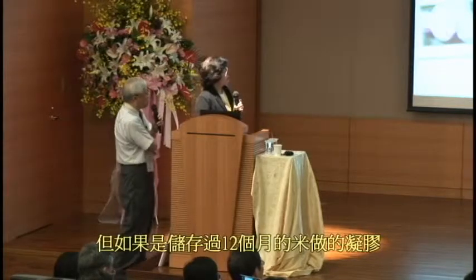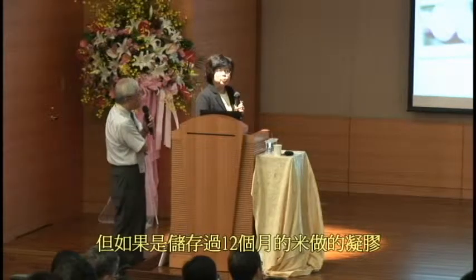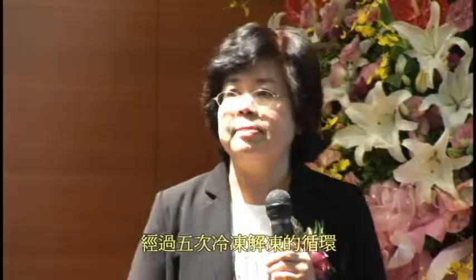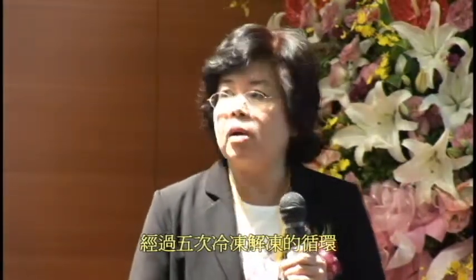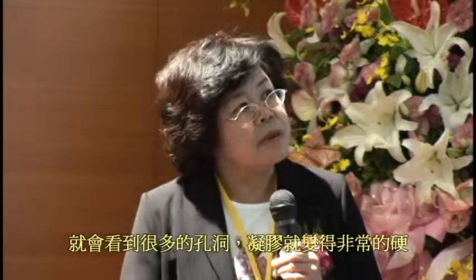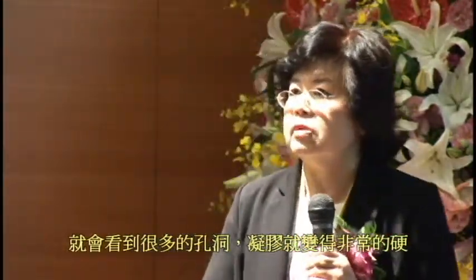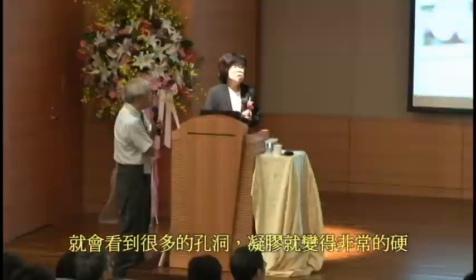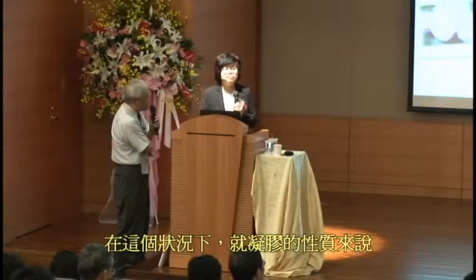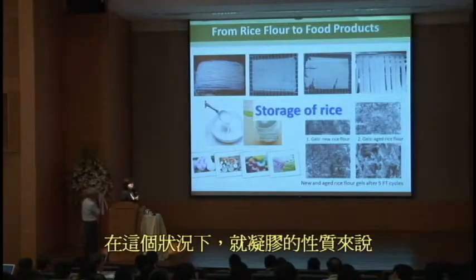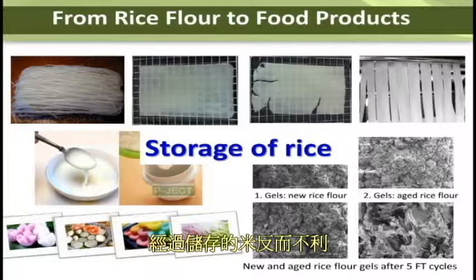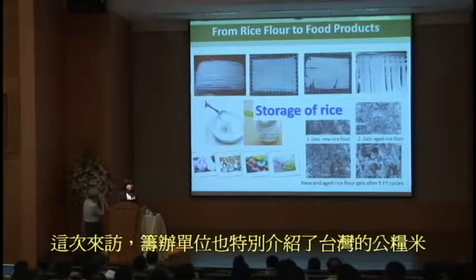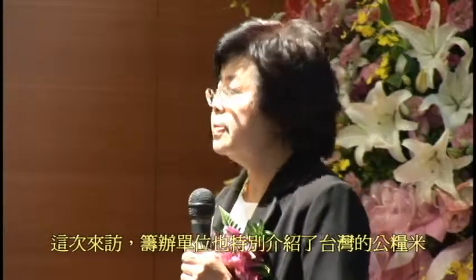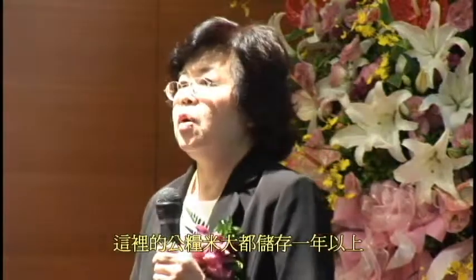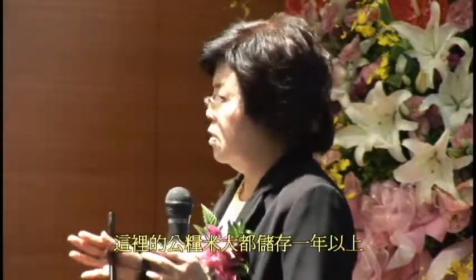But for the gel made from aged rice flour of 12 months, you can see there is a change in the microstructure. There are some pores or holes. Besides the microstructure, the texture of this freeze-thawed gel is harder. So in this case, the aged rice flour is a disadvantage. So you can see that the storage of rice affects the quality and characteristics of the rice product. I also heard that in Taiwan, for the purpose of food security, you also store some rice for 1 year.